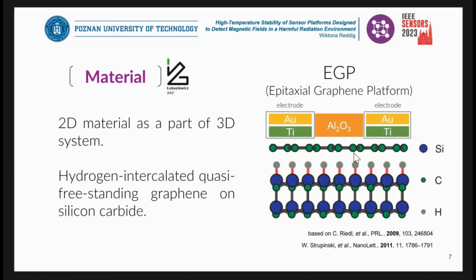For this reason, we intercalated graphene with hydrogen so that it will not be connected with the substrate and gain quasi-freestanding qualities. It is also passivated with Al2O3 to prevent absorption of any impurities, and is also equipped with golden electrodes and a titanium buffer layer for better contact resistance.